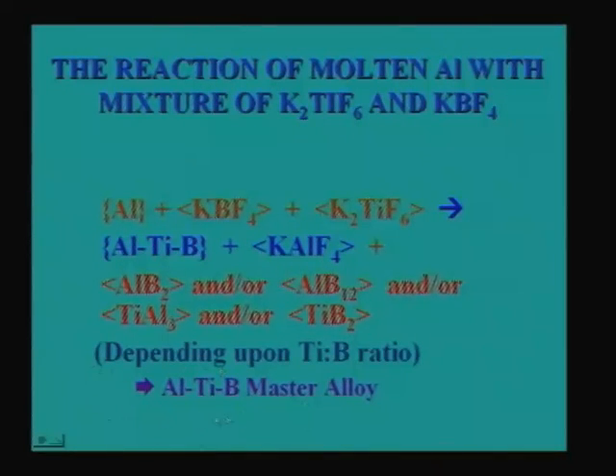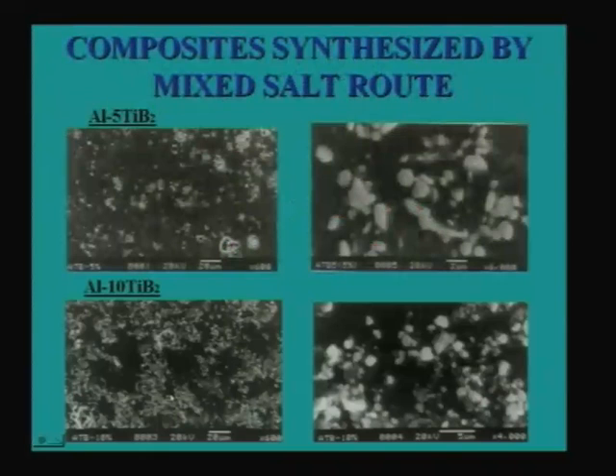So the control that you need to exercise is much more than what you do in case of aluminum titanium boron master alloy, which is made for the grain refinement of aluminum alloys. So if you do that, you end up with TiB2 particles definitely, but one has to control. These are all after controlling various process parameters. This is for 5% TiB2, this is for 10% TiB2. As you can see, in 10% TiB2 you will have more volume fraction of TiB2, which is what is expected. Whatever percentage that we are talking about here is weight percent, and one has to convert it into volume percent.